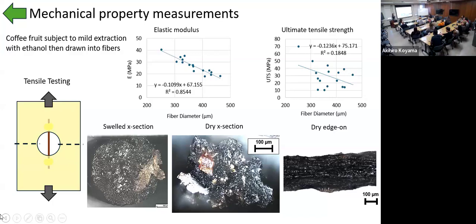And that can be good for linking into a matrix. If you're trying to epoxy embed these, that gives you a lot of surface area to adhere to. But if you're looking at tension, these are crack propagating surfaces. So every one of these sharp edges that happens when my fibers dry is a point of failure. And so we have a geometry problem of being able to go from a paradigm where we start with these nice round surfaces that are very strong engineeringly and geometrically to a very weak structure that needs some consideration on how we access better surface area when we are fighting the laws of physics.